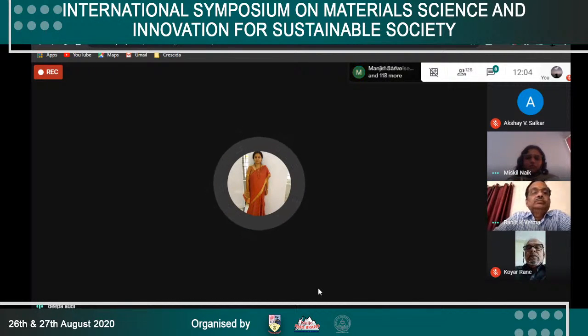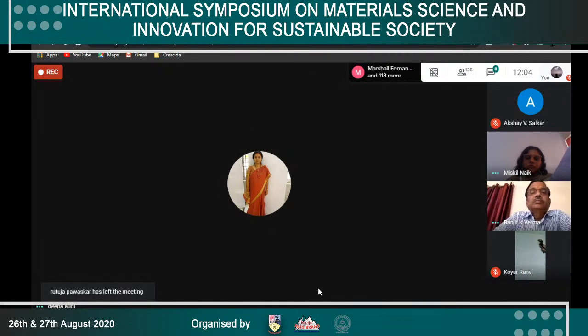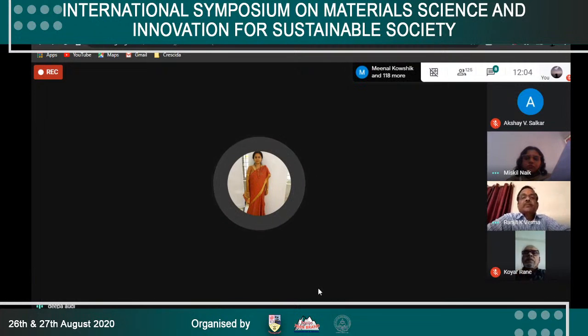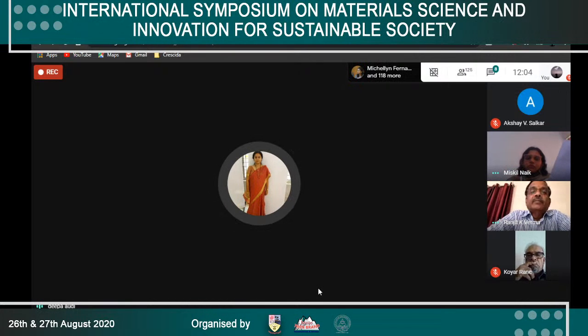It was a very good presentation. I would like to ask one question. Barium ferrite, as you said, is a hexaferrite. Now, if we dope this barium ferrite with a transition metal, say nickel, then nickel normally occupies the B site. So it would lower the concentration of ferric ion in the B site. So will that lower the magnetic saturation value and its magnetic properties?